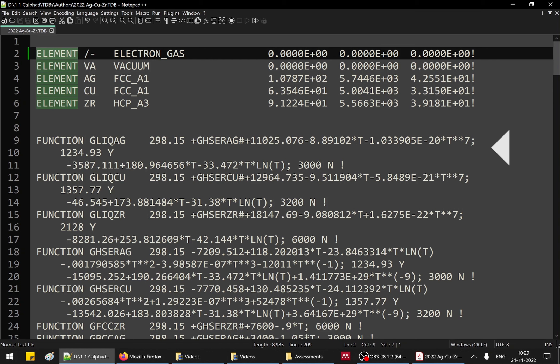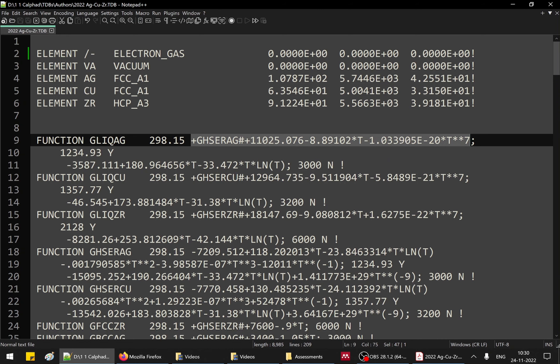You can see a function called G_liquid_Ag — silver's Gibbs energy in its liquid state. Although silver does not exist in liquid state at 298 Kelvin, we still have a description for liquid silver at that temperature. This comes from the SGTE database — Scientific Group Thermodata Europe — which has standardized the unary descriptions for single element Gibbs energies in different crystal structures: FCC, BCC, HCP, and liquid. From 298 K to 1234 K, this is the Gibbs energy description for liquid silver.